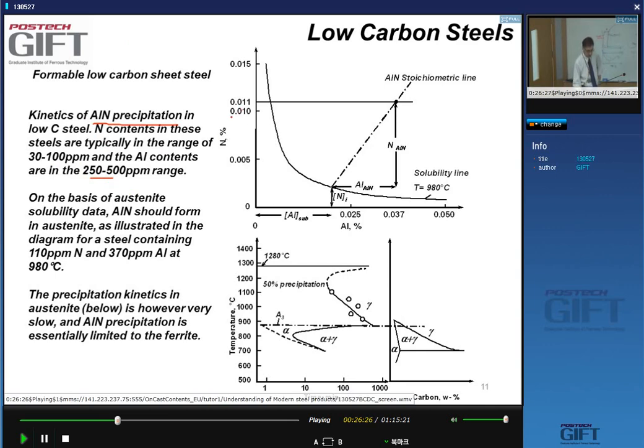So let's see what situation we have here if we assume there is 110 ppm of nitrogen and about, say, 370 ppm of aluminum in our steel. And we look at the graph of the solubility of aluminum nitride in austenite to start with. Then at 980 degrees C, this is the solubility line.